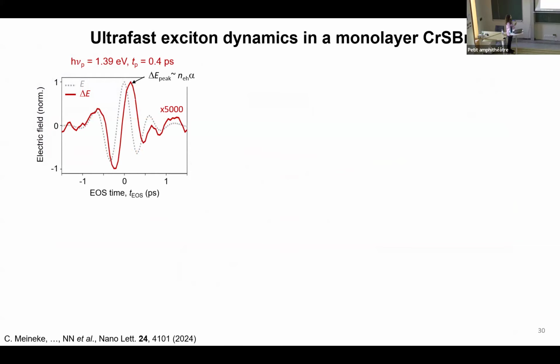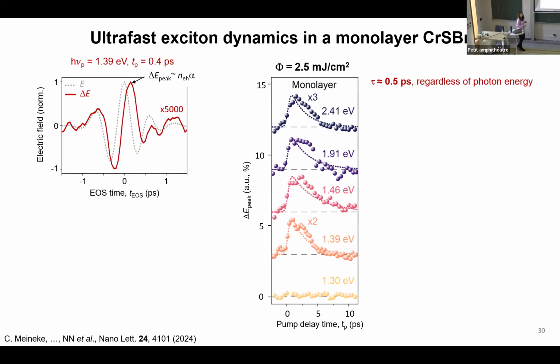Here I show you the scattered electric field of terahertz radiation to the far field. Overlaid is the pump-induced change, that is when we have generated excitons. What we do is that we sit at this maximum and we scan it for different pump-probe delays. And we do it for multiple photon energies, as I showed you the spectra in a few previous slides. What the data is suggesting is that we have an ultra-fast relaxation dynamics.